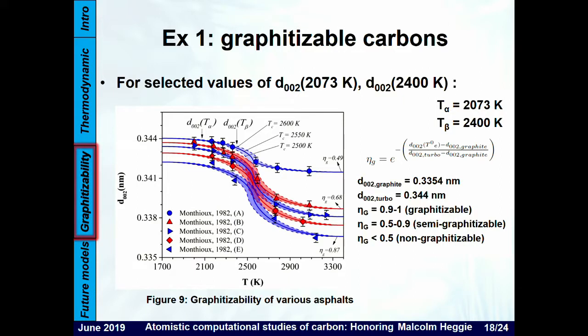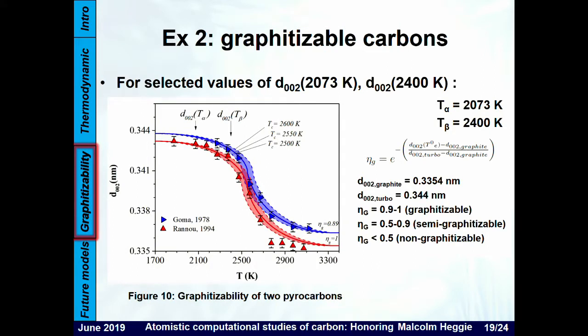So what we did after that is extend the application of the model to a lot more graphitizable carbon, which I will not show here for the sake of respecting the time. But what's interesting is that the model seems to work as well for pyrocarbons and other carbons which are more typically obtained from classical processes, such as the heat treatment of petroleum products. So there seems to be a parallel between the two mechanisms for the graphitization of classical carbons and pyrocarbons, which is captured by the present model.